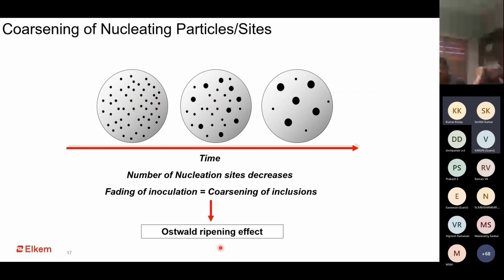The concept is called ripening. Ostwald was the scientist who found this, and based on his name, this effect is called the Ostwald ripening effect, where these small nucleating sites basically ripen. They become bigger, and as they keep becoming bigger, the number of nucleating sites keeps coming down. And as the nucleating sites keep coming down, the inoculant effect keeps coming down, and that is what we call fading of inoculant. What do we want to do? We want to make sure that our casting happens sometime here. Not the solidification, but at least the casting should happen around this time, so that you have a sufficient amount of nucleating sites for the graphite precipitation.